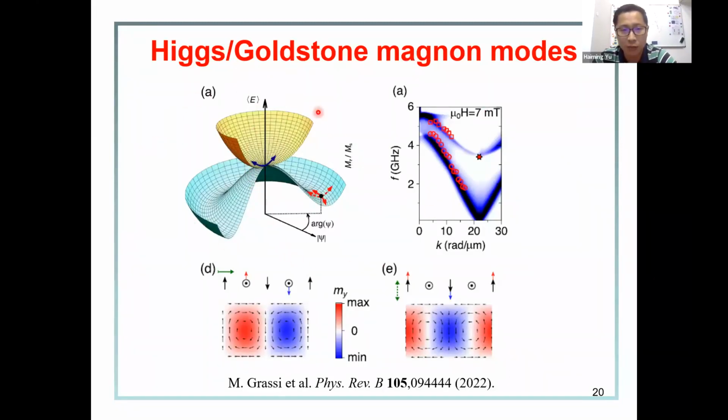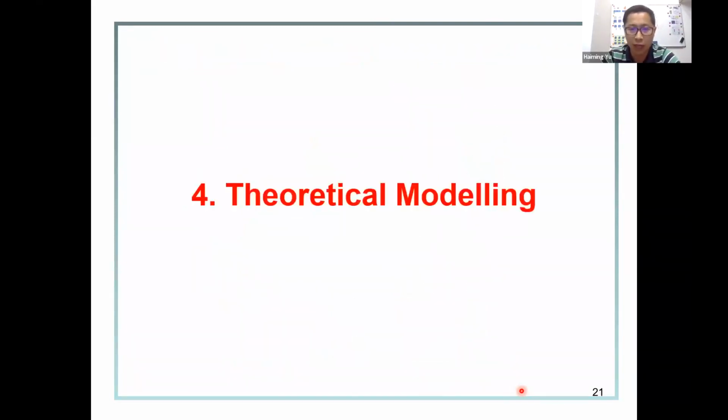If you consider the magnonic band structures, you can see one in low frequency, one in high frequency. They have these two particular modes, and these modes go down with higher wave vectors. The low frequency mode, in their drawing, is more like the wall part, the domain wall part. And the high frequency ones are more focused on the domain volume part. So this is consistent with our experimental and also simulation works. We have learned quite a lot from this new paper.